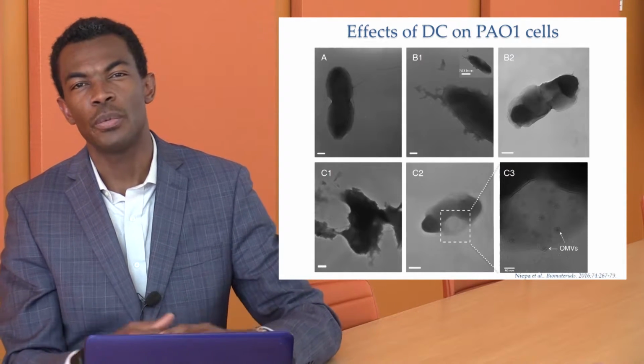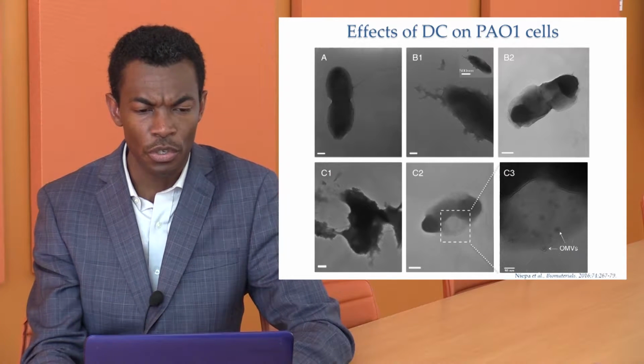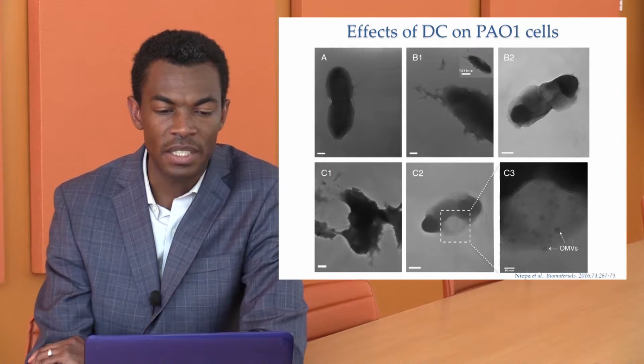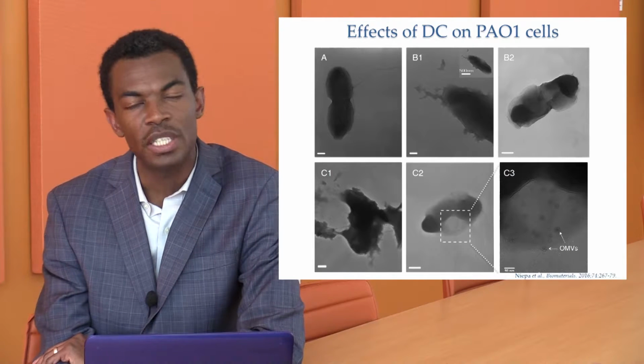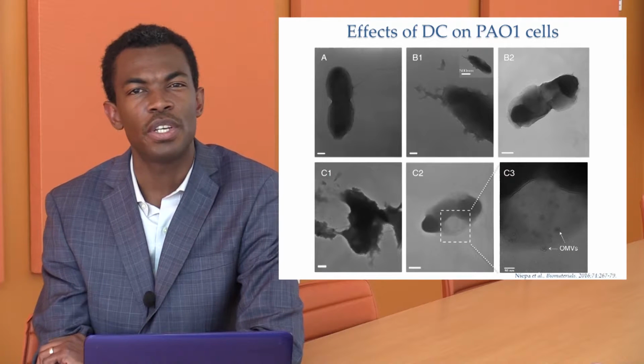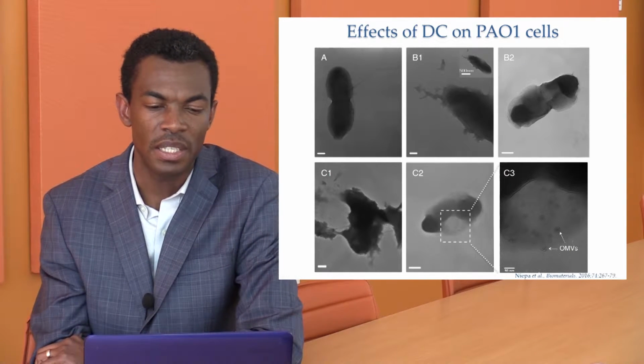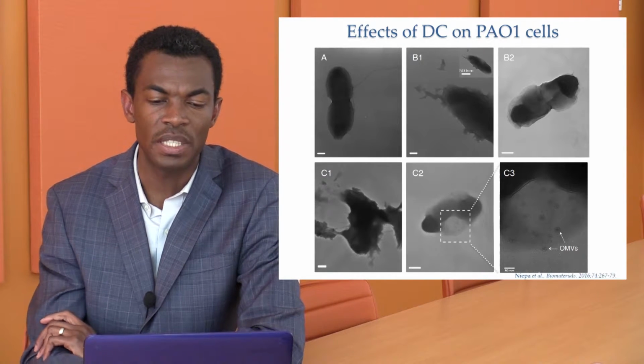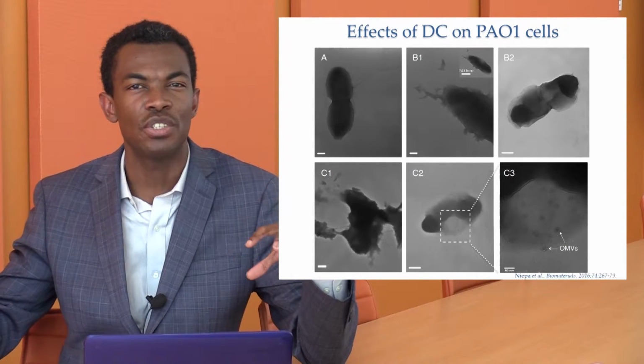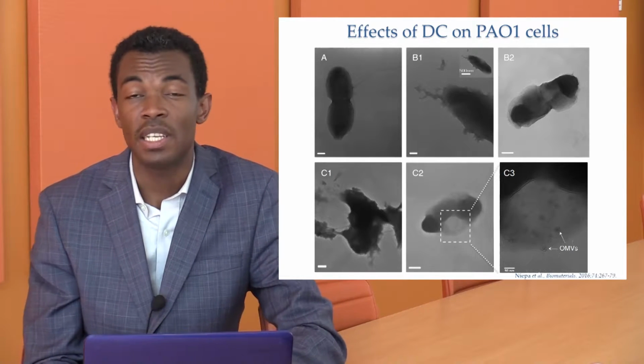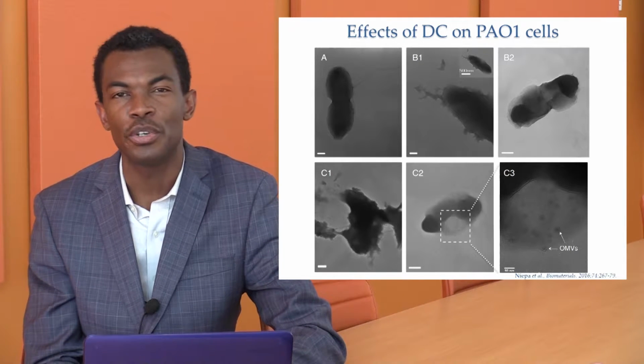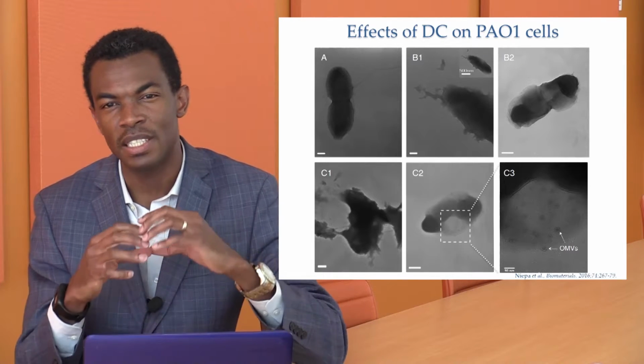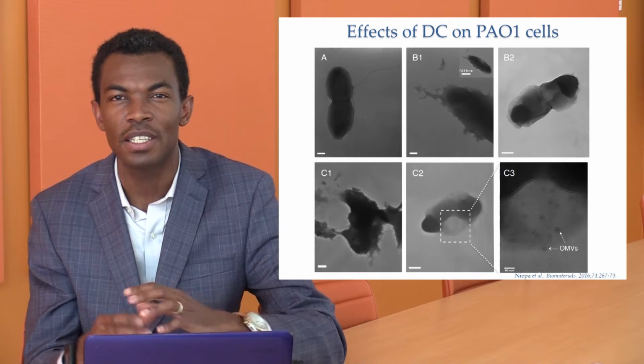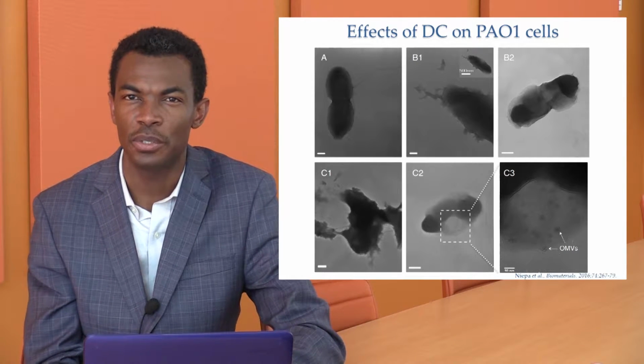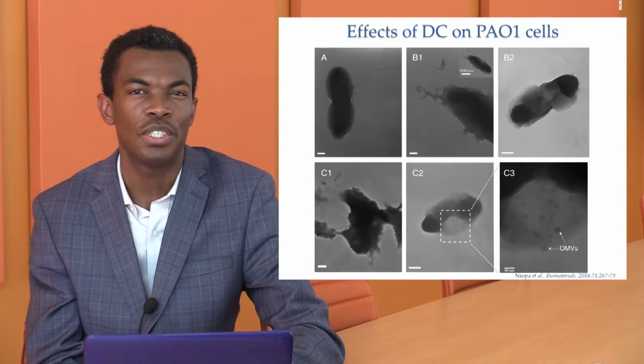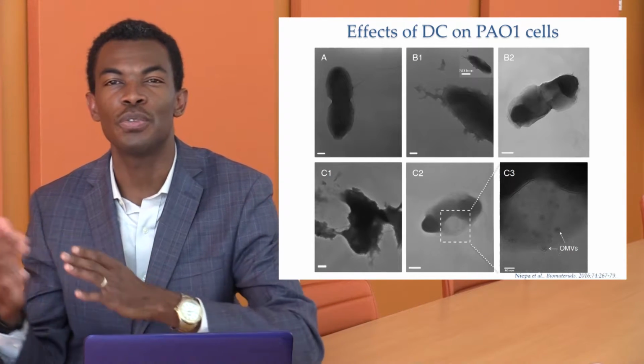But we went further to see in real time how these look like to the cells that are exposed to such treatment. So for the control, we see that the cells look nice, intact. That's our figure A. But when the cells are treated with carbon electrode, figure B, we see two main configurations of cell morphology. The cell membrane is completely lysed. As we can see here, we don't have a very nice intact cell membrane. And also the second morphology was that we saw some type of localization of some dark compartment at each part of the cells. When the cells are treated with stainless steel electrode, shown in figure C here, we also see those specific configurations where the cell is completely lysed, or maybe the cells start producing something that we call OMVs, outer membrane vesicles. And usually when this happens, it means that cells are under certain stress. So this is already some clue for us to follow up with a genetic study.